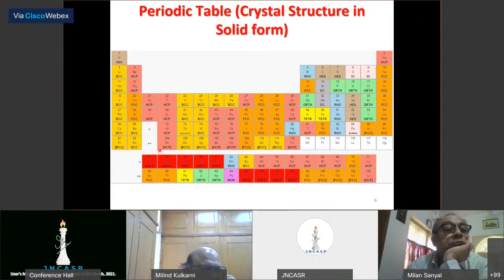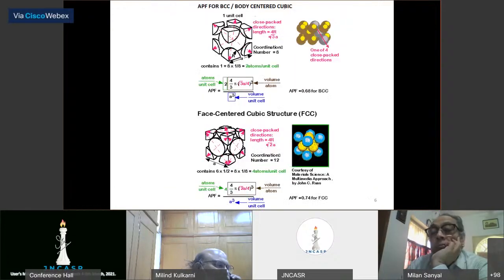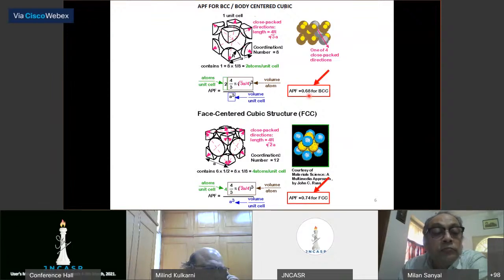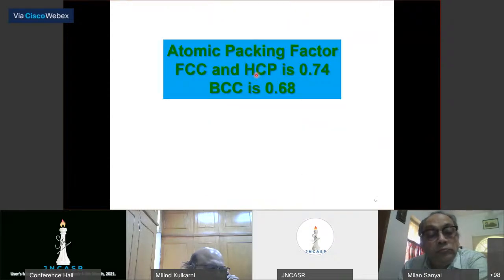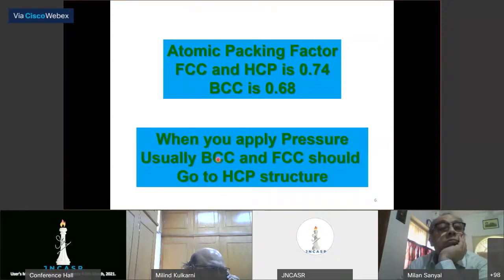And here is a periodic table which says that most of the materials are FCC, BCC, and some of them are HCP. And there are some other crystal structures, very rare in the periodic table. So the basic crystal structure is because of the packing fraction. You can see BCC has a packing fraction of about 0.68, and FCC has 0.74. In general, the atomic packing factor is 0.74 for both FCC and HCP, and BCC is lower. So it is very well known that BCC and FCC would transform to HCP as the pressure is increased.